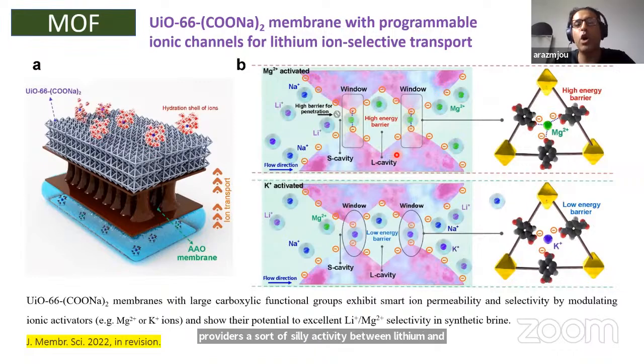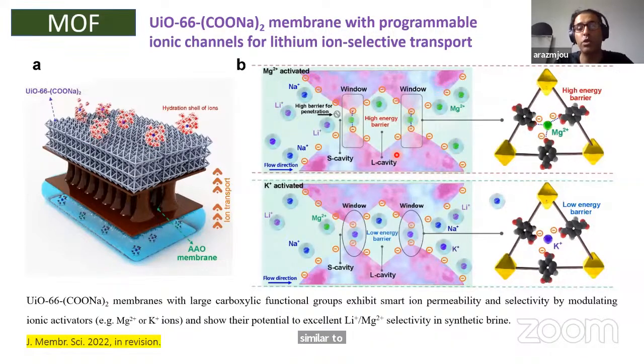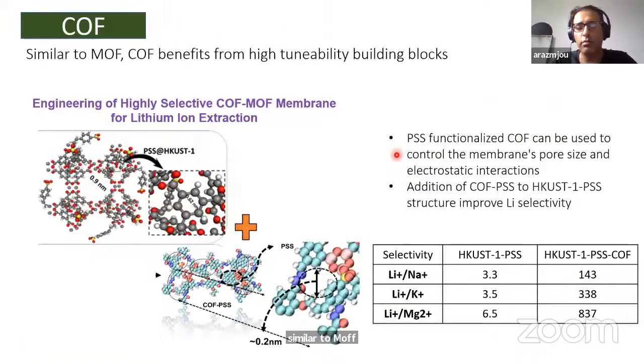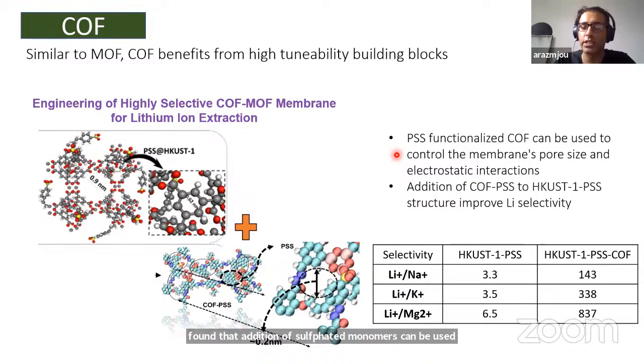Similar to MOF, COF, covalent organic framework, they are also very good building blocks for making lithium selective membranes. We found that addition of sulfonated monomers can be used to control membrane pore size and electrostatic interactions, and that substantially increases the lithium ion selectivity.